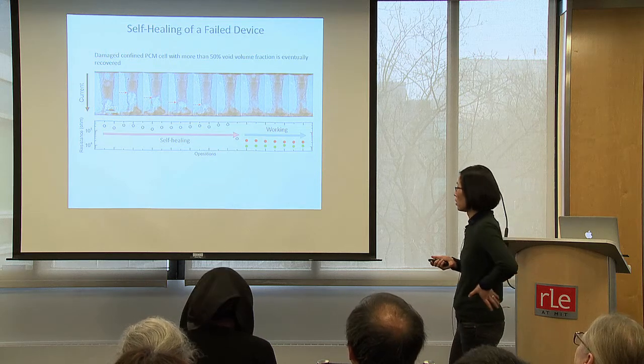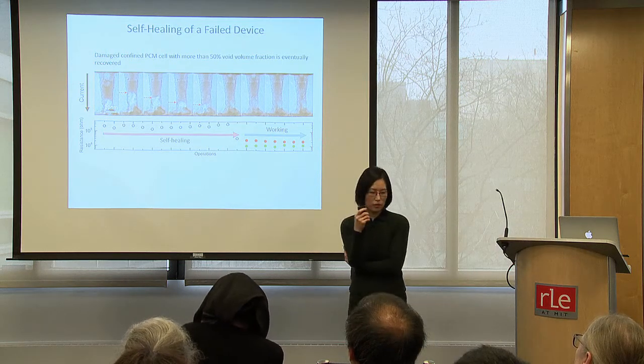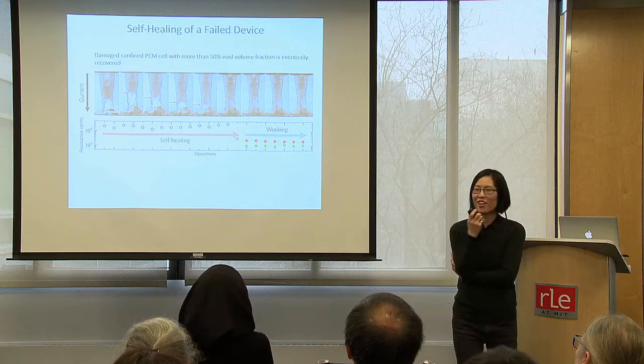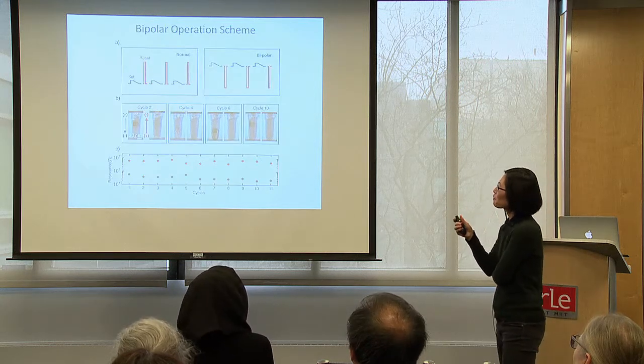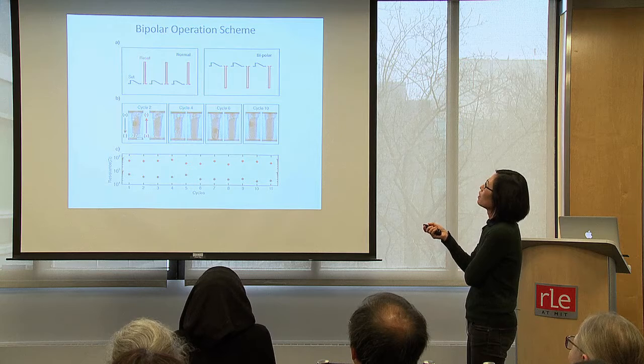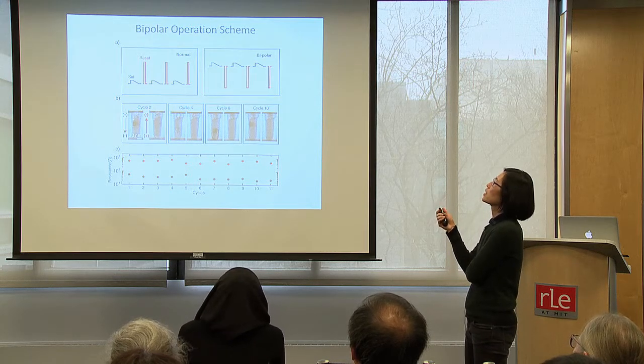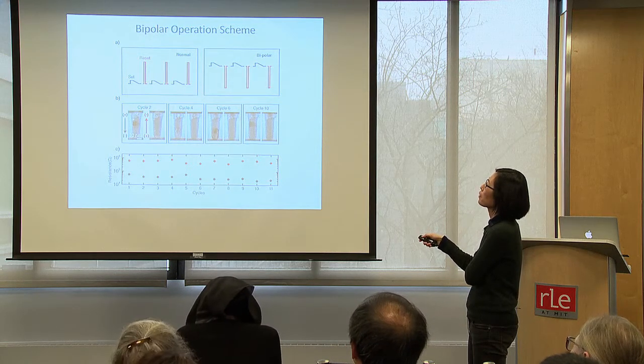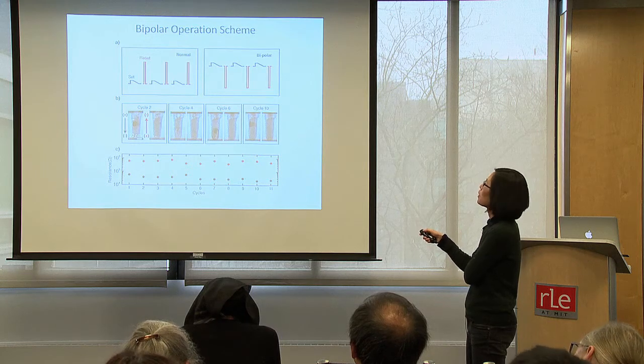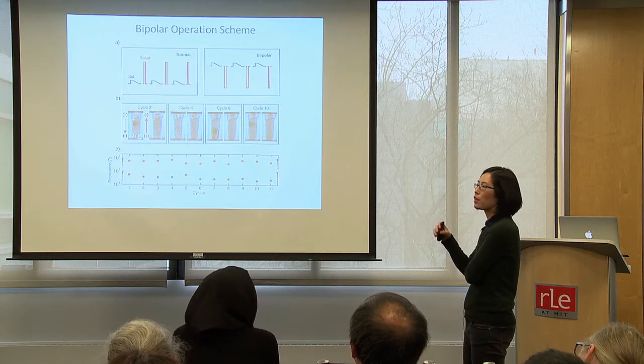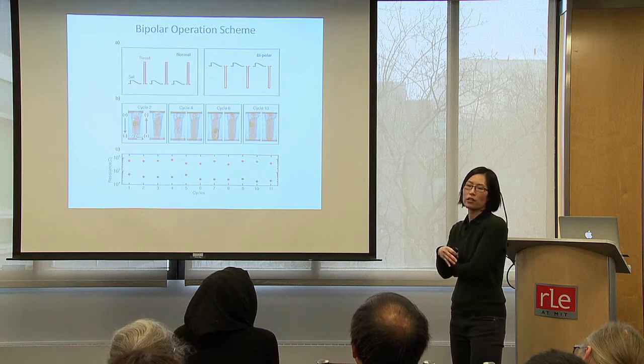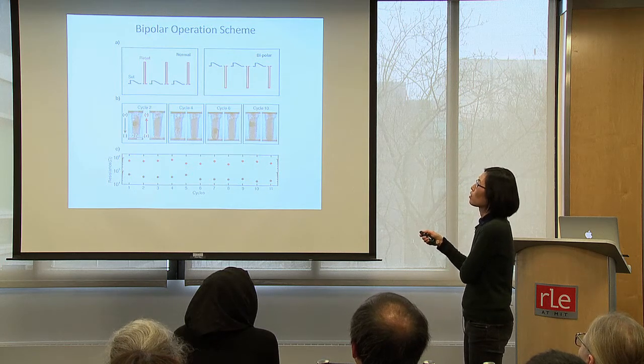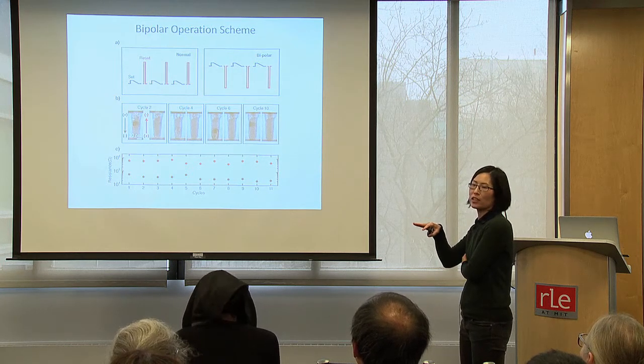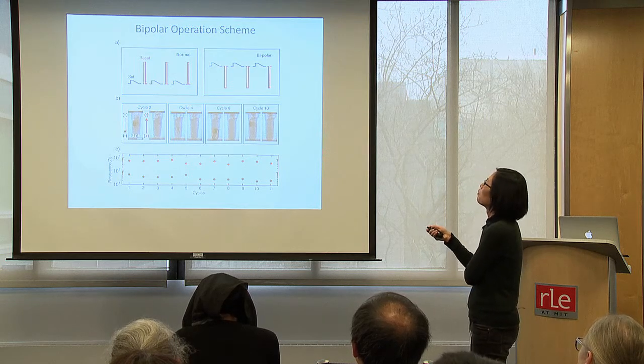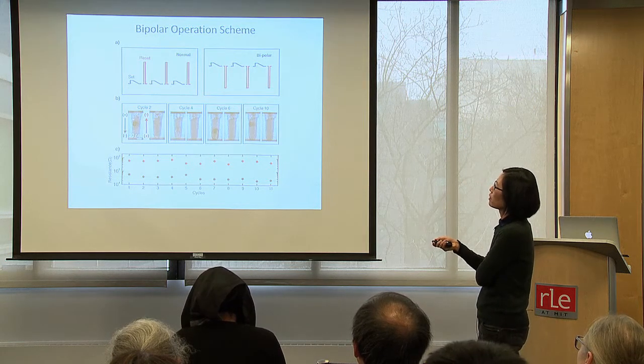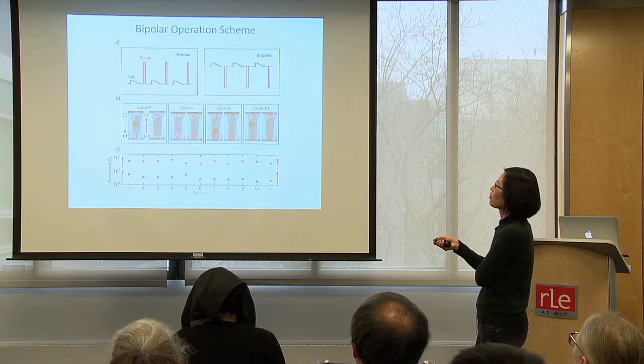I couldn't resist myself from calling it self-healing. So maybe a take-home message could be that instead of using the same polarity for the set and reset, maybe use an opposite polarity. So if the antimony moved up, you try to move it down the next cycle. This is actually a lot of overhead design in the wafer scale. But as an idea, we proved that this way of running the device works.